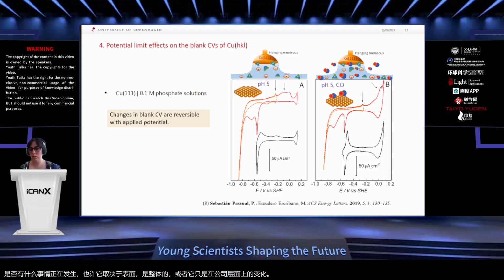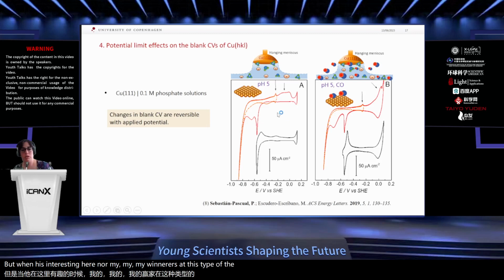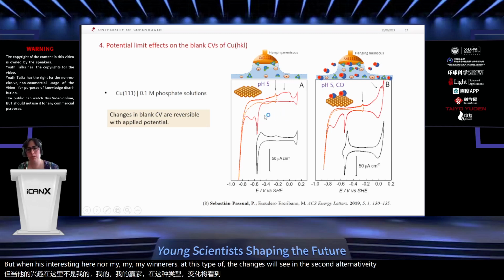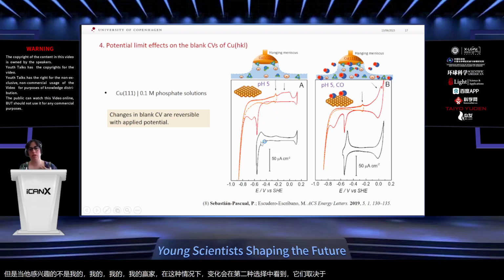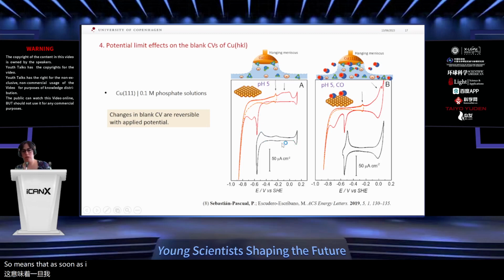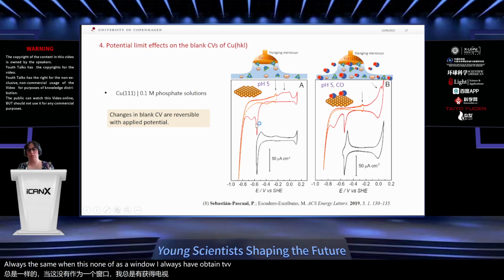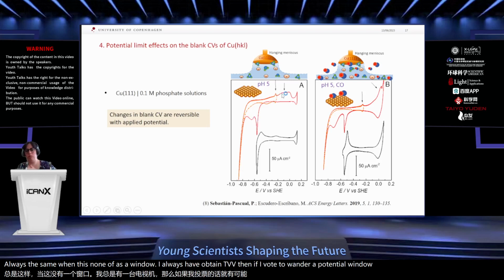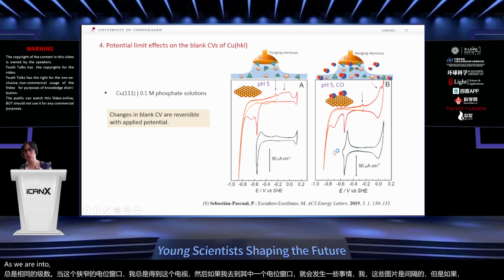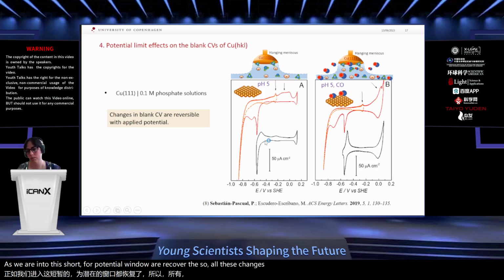But what is interesting here, from my opinion, is that this type of changes we see in the cyclic voltammetry depend on the potential. So as soon as I change the potential limit conditions, I always obtain the same CV. In this narrow potential window, I always obtain this CV. Then if I go to a more negative potential window, something is happening and the feature is displaced. But then if I switch again to this short potential window, I recover the feature. So all these changes seem to be reversible with potential window.